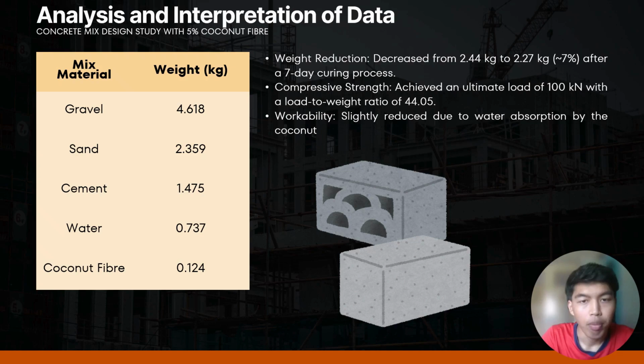During testing, the brick withstood an ultimate compressive load of 100 kN. The fibers significantly improved the concrete toughness because they bridge small cracks and delay crack propagation. Ultimately, the 5% replacement proved highly effective in creating a strong, lightweight, and sustainable construction material.